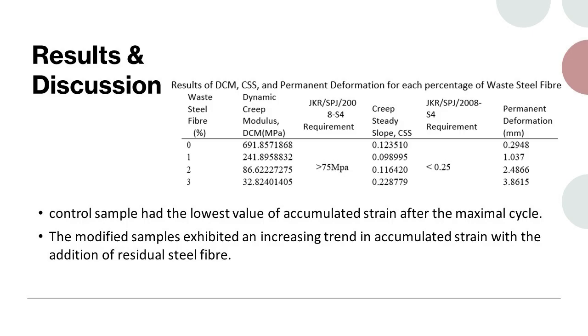According to the data of accumulated strain recorded in the table, the control sample had the lowest value of accumulated strain after the maximal cycle. The modified sample exhibits an increasing trend in accumulated strain with the addition of waste steel fiber. The rutting performance of waste steel fiber as an additive in the asphalt mixture was evaluated using three parameters: dynamic creep modulus, creep steady slope, and permanent deformation.